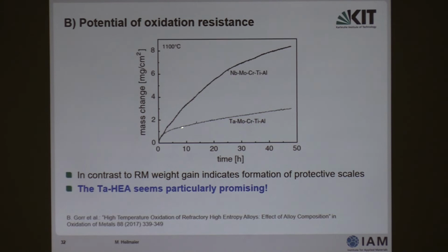What we need is a parabolic scale, so this should become slower and slower and slower, and then after 50 hours, there's not much more metal consumed. So you have to check whether you have a parabolic growth law or not. And this alloy does show parabolic growth. And of course, at the moment, in this scientific community, we know only of these three elements, and some mixtures of them, which show parabolic growth at elevated temperatures. If you find another element, you can become very famous.